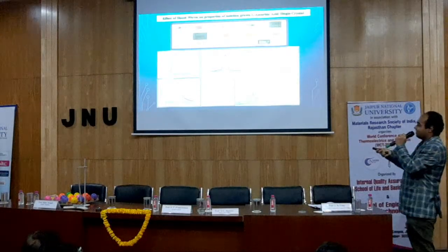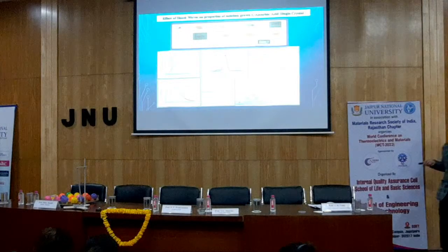But we see the effect of shock, that the quality is improved, and further you can see the PL intensity has gone down, the defect density is reduced, and the non-linear third order optical coefficient has also been enhanced, indicating its use for optical switching applications. So this can be one of the approaches that we can use for reference material production. These three approaches we have designed and we are trying to incorporate with other materials so that we can get such crystals that can be used for reference material at NMI.